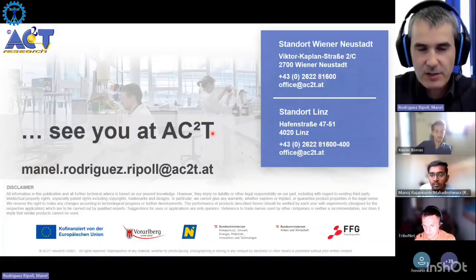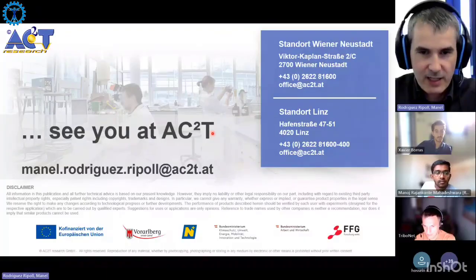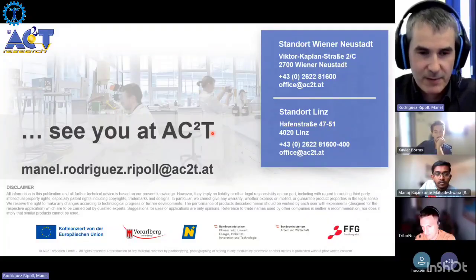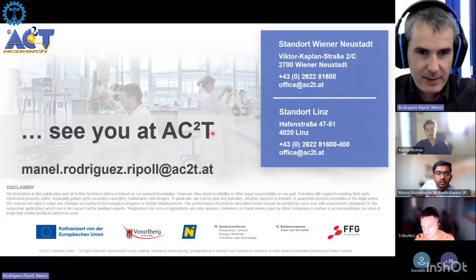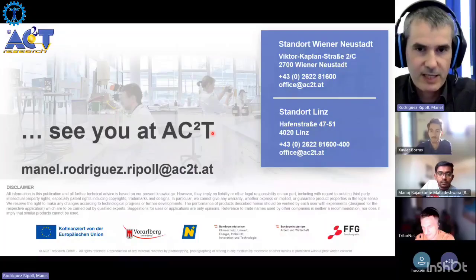But basically, doing this frequency scan, you can track or trigger many phenomena that are time dependent in the electrolyte, like double layer formation, and you can get information of, for example, different phenomena that take place at different time scales, like ion motion that maybe is a slow phenomenon that will occur at lower frequencies. So if you want to observe all these kinds of phenomena, then EIS is the proper way to go.